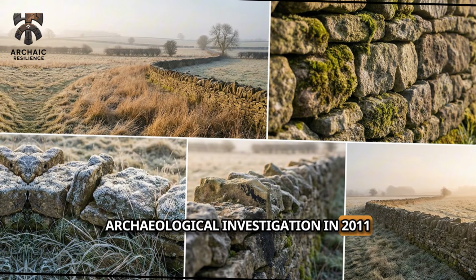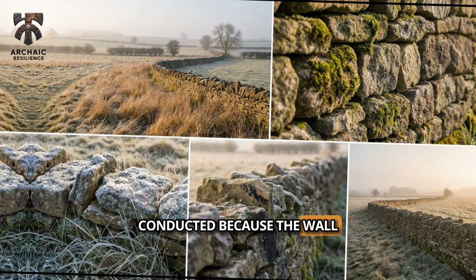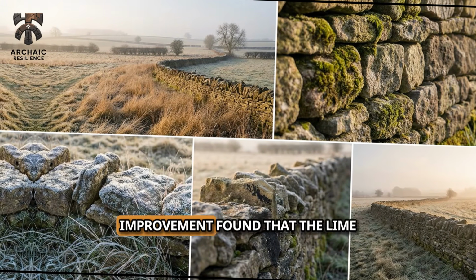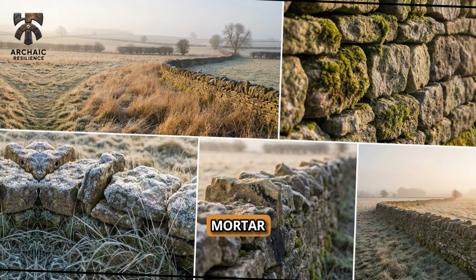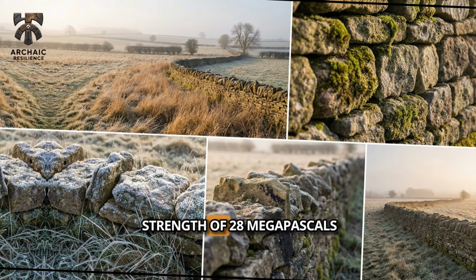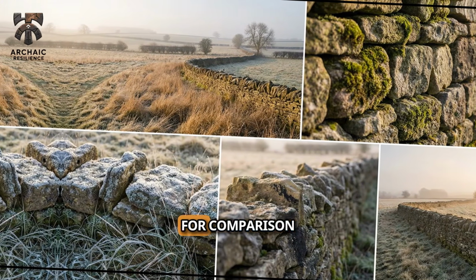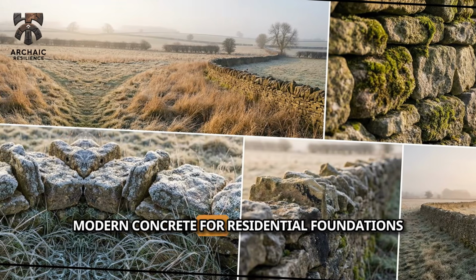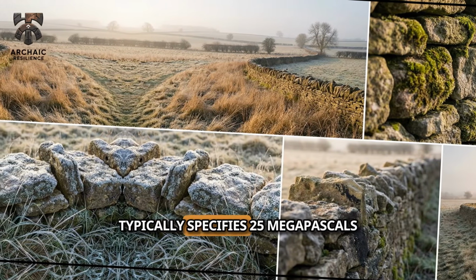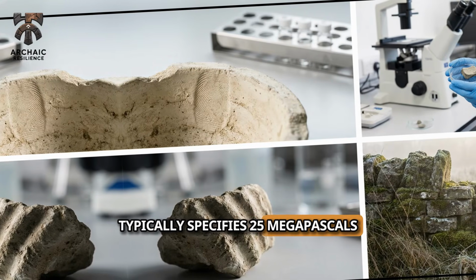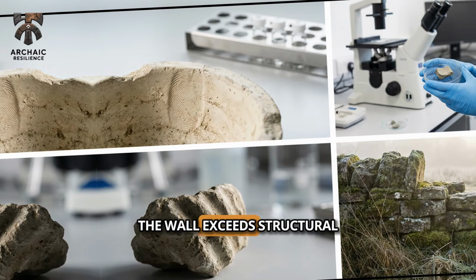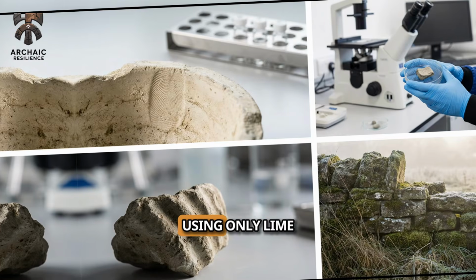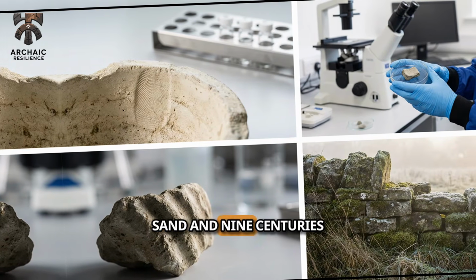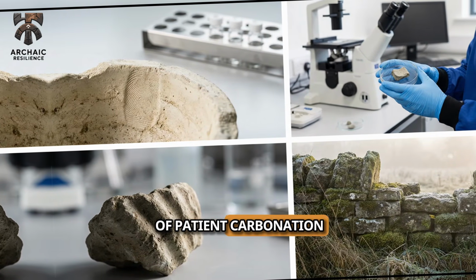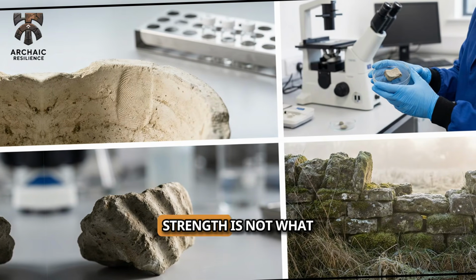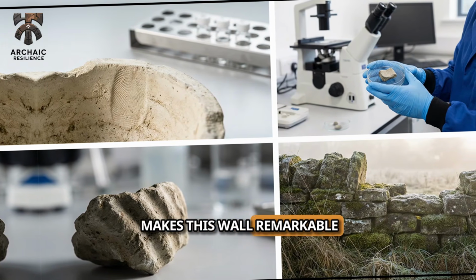Archaeological investigation in 2011, conducted because the wall happened to lie in the path of a proposed road improvement, found that the lime mortar had achieved a compressive strength of 28 megapascals. For comparison, modern concrete for residential foundations typically specifies 25 megapascals. The wall exceeds structural concrete specifications using only lime, sand, and 9 centuries of patient carbonation. But compressive strength is not what makes this wall remarkable.